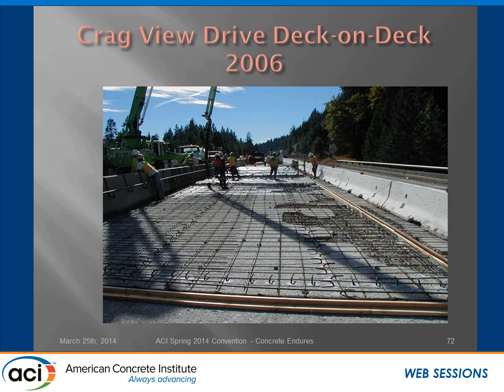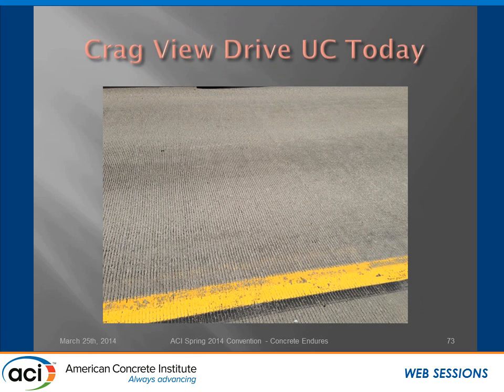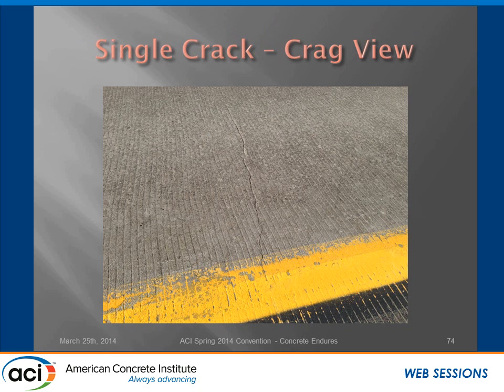I did want to point out one thing here. A lot of experience that we've had in the past, we've either tried to rub grout in on these patches or use old to new concrete epoxy and things like that. And it's been my experience from doing these for 30 years that a simple water, saturated surface dry, get the puddles cleaned off, seems to work best. The guys selling the products probably don't want to hear that, but that's been our experience. This is that bridge today, and there's no cracks. Well, there is one small crack here. I think that's a structural crack over a bent cap, but it's looking pretty darn good. And that's in chain wear, and it's pretty high volume truck traffic.